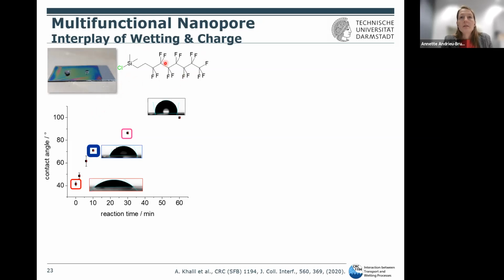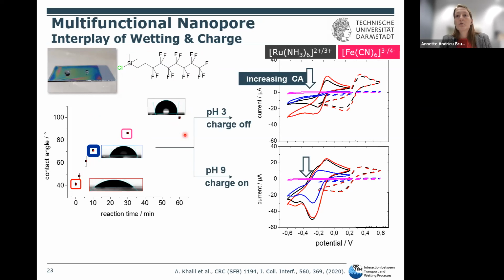What we did is just gas phase deposition of a perfluorinated silane. We observed that we can tune the macroscopic contact angle from hydrophilic, so unfunctionalized, to hydrophobic and water exclusion. Then we used these films to measure cyclic voltammetry, so pore accessibility. What you see is that with increasing contact angle, looking at the positively charged probe molecule, for example, the pore accessibility is reduced and even completely blocked. You see this for both probe molecules. And you still see a pH influence, which is logical, because even if you functionalize here, silanol groups at the pore wall remain. So these are switched on if you go to basic pH.